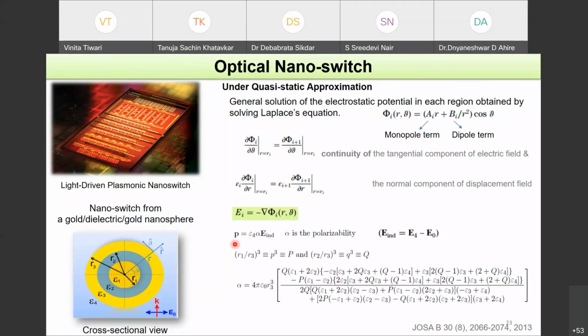expressions. The final expression would be like the polarizability is epsilon4 alpha and then electric field which is incident. So when you do the calculation, you can obtain the polarizability alpha of the nanoparticle. So as you can see here, it depends mostly on the material permittivities and the dimension of the nanoparticles. And once you obtain the polarizability, your technique is very straightforward. You can obtain scattering cross-section straight from this particular formula.